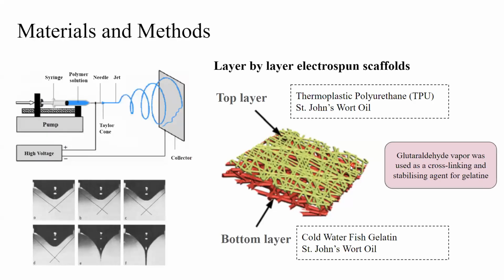In the electrospinning setup, the polymer solution was placed in a syringe and set on a syringe pump to control the flow rate. The syringe needle was connected to a power supply and an electrically grounded plate was used as a collector. When the electric voltage is given, an electric field grows and it causes charges to be generated in the polymer solution. A single droplet comes to the tip of the needle, and normally it would have a spherical form due to the surface tension. But the electric field deforms this spherical form, and as we can see here, a conical shape forms, which is known as the Taylor cone.